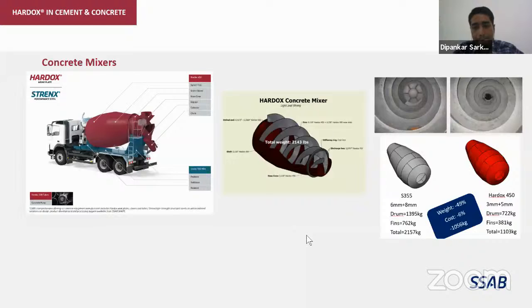In this case, I've chosen one example. If you take a look at the left side picture, you see the drum itself in the red color, which is produced from Hardox, and the chassis in the blue color, which is produced from Strenx material, Strenx 700. And then inside, we have the drum shell, and we have the fins in the middle. Most of the wear is usually on the fins. The drum is having wear, of course, but the fins are the highest affected part.